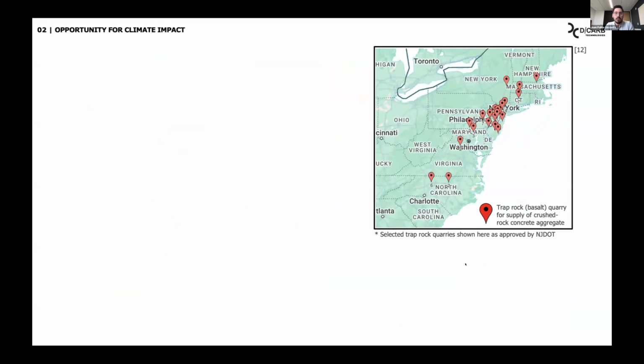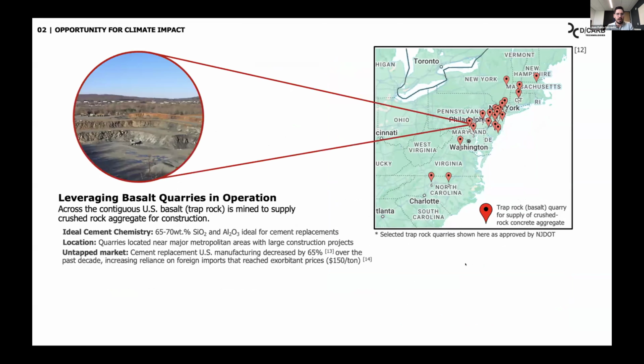Now, when we're looking at decreasing cement use, let's look at trap rock. Trap rock turns out to be basalt, and it's actually a basalt that is quarried and used for aggregate. So here you have a few of the quarries for trap rock that we have on the eastern coast of the US. Now, this is a picture of one of these basalt quarries. So it turns out we already are mining basalt, and basalt has an ideal cement chemistry composition, with between 60 and 70% by weight of silica and alumina, which makes it a really good cement replacement. However, it doesn't react. We'll get to that part later on.